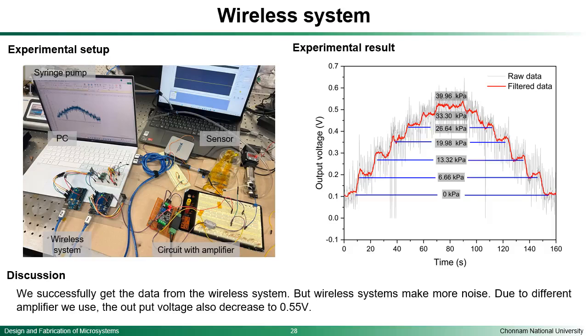Then we use the same sensor to do some basic tests in the wireless system. At the same time, we connect the sensor's output wire to the Arduino board, and we apply the pressure with the syringe pump. Here we can see that because we use the wireless system, the noise is much more visible than before. Also the sampling rate is different. When we use the wired system, the sampling rate is much higher, and when we use the wireless system, the sampling rate is something like 10 points per second, which means the sampling time is around 100 milliseconds. We can still get the signal, and after filtering, I think the signal is clear enough. The output voltage decreases to around 0.55 volt.